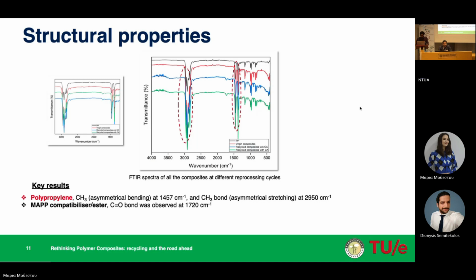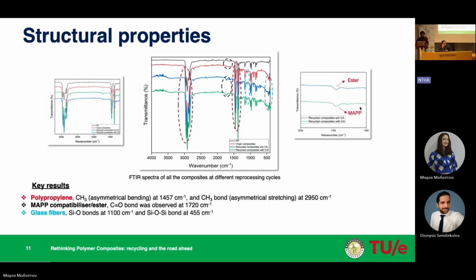And similarly, we were also able to see the peaks which correspond to the ester linkage, which already exists in the wind turbine blades. And we are also able to see the peak which corresponds to the carbonyl bond, which is for the MAPP coupling agent. And also, we did not observe any alterations in the glass fiber peaks as well, which indicates that there was no significant structural change happening within the composite. Mostly the degradation which we can see would be thermo-oxidative degradation, but sorry, it is actually not thermo-oxidative degradation which is taking place, but rather thermomechanical.